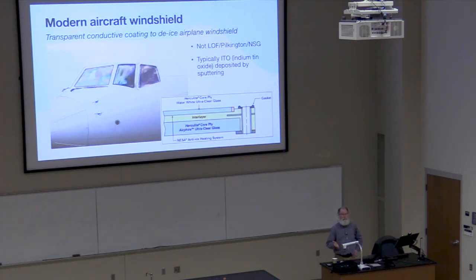So, modern aircraft still use TCO coatings on their windshields. This is an older photograph, but you can see the colored reflection here. It's kind of like oil on water. You get that colored reflection because of the thin layer: you get a reflection from the top interface and the bottom interface, and depending on the thickness, those two reflections interfere constructively to give a color. So the blue color is a different thickness of coating than the red color.